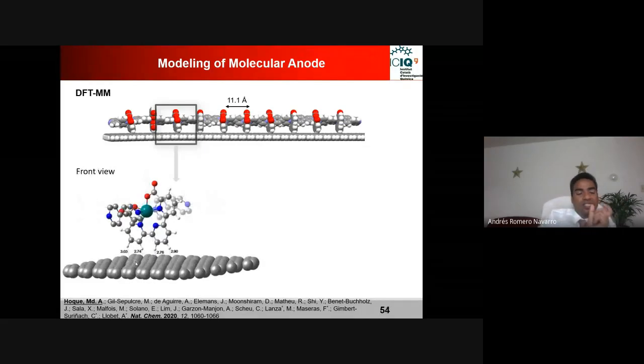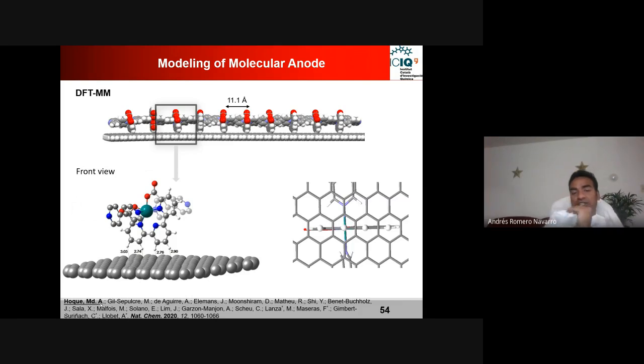And then we see this from the front side. What we found is that each of these units has such a low distance with 4 different CH bonds. And then we thought, okay, there must be something happening with these 4 CH bonds with the surface per each unit of this ruthenium center. If we just rotate it, we can see this white is showing the hydrogen bond, and the benzene ring, whatever is showing, is basically the graphitic material.